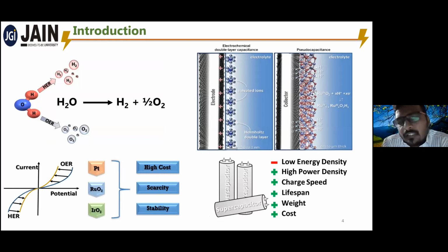Basically, in the water splitting reaction, two reactions take place. One is the hydrogen evolution reaction, which takes place on the cathodic side, while the oxygen evolution reaction takes place on the anodic side. Currently, the problem with water splitting is that it is slightly sluggish. Both these reactions are sluggish. They require more potential to generate the current densities, and the best or suitable catalysts we find nowadays are platinum or ruthenium and iridium based catalysts.